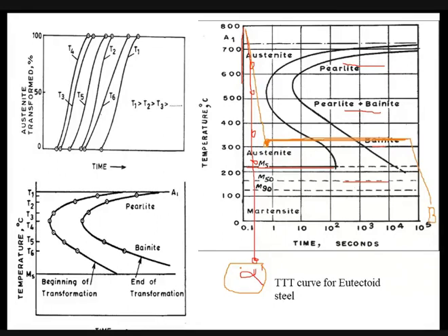So carbon atoms are present in austenite at octahedral sites, so they are trapped there itself. There is no time for carbon atoms to diffuse out. If you allow time for diffusion, then carbon atoms can displace from their positions, but here you are not allowed time. So they are trapped in their sites, and that's why distortion occurs, and you will get a supersaturated solid solution.